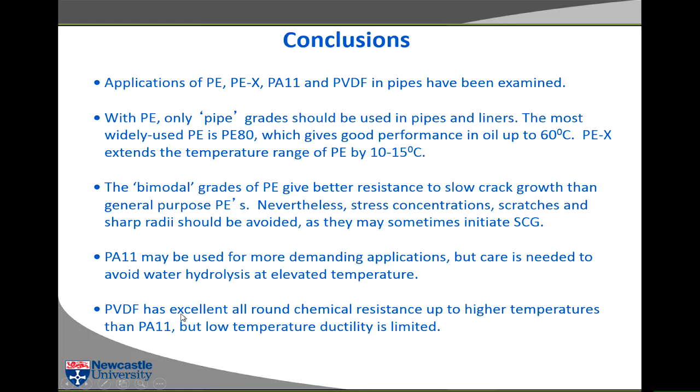PVDF is also very good, has excellent chemical resistance up to higher temperatures, but at low temperatures the ductility is limited. So when you go and visit Wellstream, you'll see the liner being extruded around the steel carcass of the pipe, and you can ask them what polymer they use, and it'll probably be PE80 or PE100, but you can ask them whether they use nylon 11 or PVDF as well, and the answer will be yes for special applications.